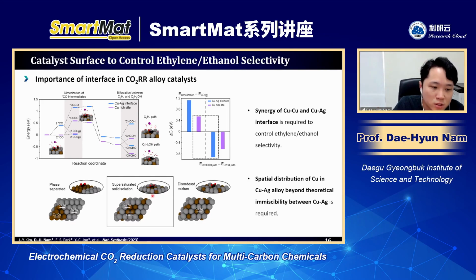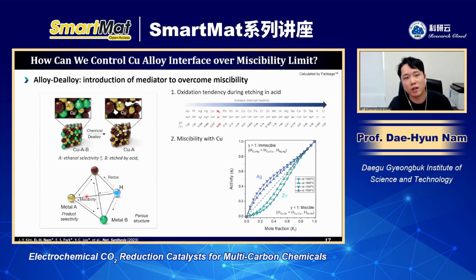But in general, from a thermodynamic point of view, copper and silver are easily separated because they are categorized as an immiscible alloy. So we had to think about how we can make this kind of supersaturated solid solution by overcoming this limited interface.